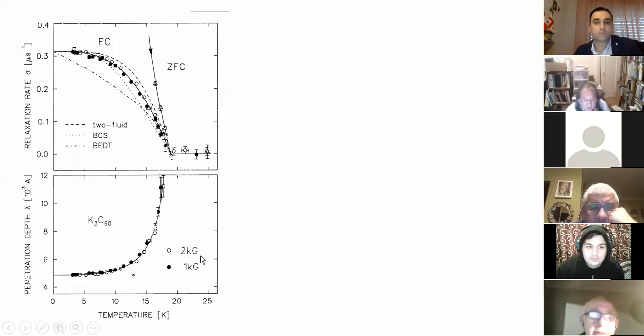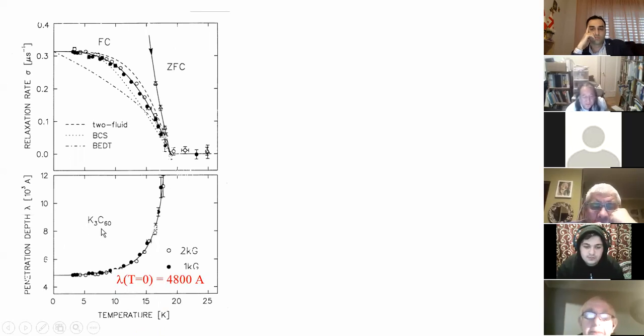And for example, this data shows that at the lowest temperature, for example, this material, buckyball material has the penetration depth of about 5,000 angstroms. Okay, so this kind of